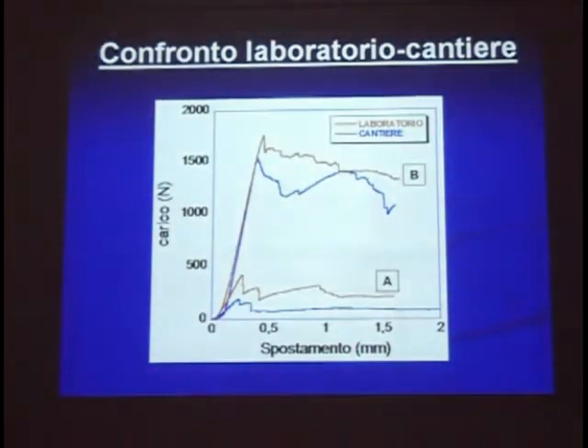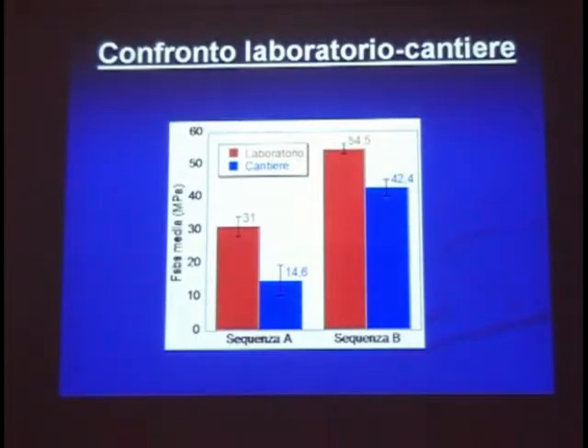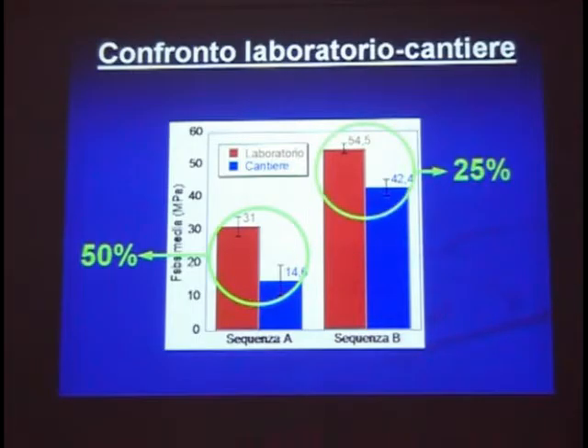And we have been comparing lamination sequences A and B from laboratory testing and taken from the shipyard. In the shipyard, you of course use different processing conditions because the hull is very big, so it's hard to control exactly in every part of the hull the temperature and the void degree. And then you get different curves from the laboratory plates. Which is very interesting is that the samples taken from the hull showed a much lower strength, up to 50% less strength than the laboratory samples. So there is a significant downgrading of the material going from the laboratory to the shipyard.